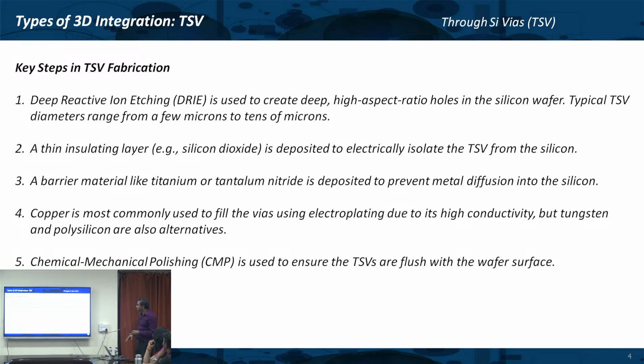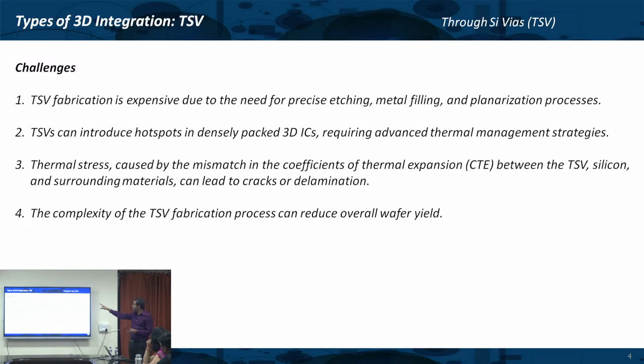And copper is most commonly used to fill these vias because of high conductivity, using electroplating techniques, but tungsten and polysilicon are also alternatives, and then you do chemical mechanical polishing in order to ensure that the TSVs are planarized. So, there is a lot of fabrication process that goes into just fabricating the via, and we are not even talking about fabricating the chips. Just to connect the chips, you have to go through this extensive process. It's pretty expensive. Okay, so the challenge is that you need precise etching, metal filling, planarization, a lot of processes,